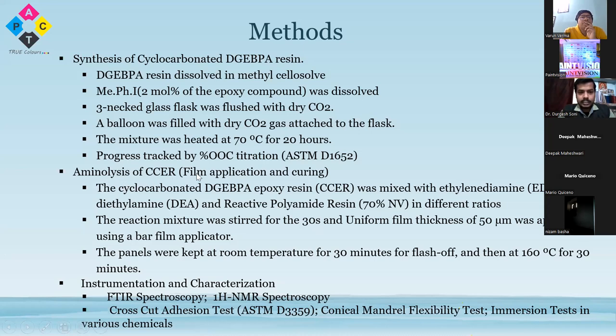And aminolysis of the cyclocarbonated epoxy resin was performed using reactive polyamide resin, ethylene diamine. And this is the application method. It was stirred for 30 seconds and a uniform film thickness of 50 micron was applied using a bar film applicator. These panels were kept at room temperature for 30 minutes for flash off.